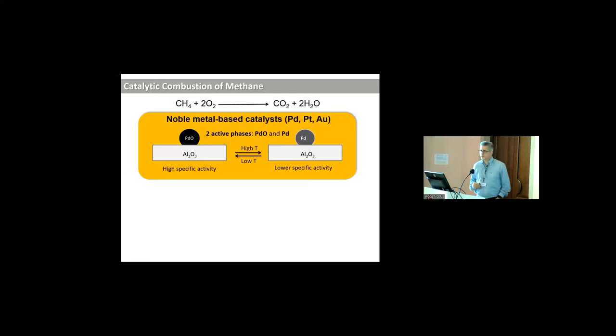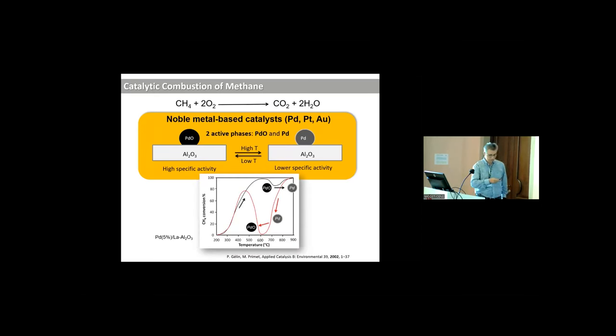So the state-of-the-art catalyst was, and still is, palladium oxide. The problem with palladium oxide is the fact that at high temperature, and indeed this type of catalyst reaches high temperatures, it decomposes to palladium metal, which is much less active. And you can see from this plot, where lots of palladium is loaded, that you have no conversion at low temperature, you go up, and while you're decomposing palladium oxide to palladium metal, you lose activity and the system is deactivated.